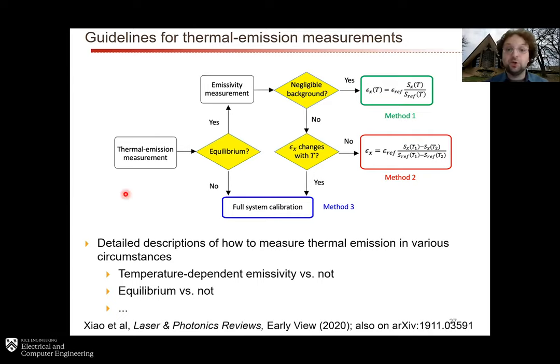And so this is a flowchart from this paper. If you ever find yourself with difficulties doing thermal emission measurements, I recommend you check it out. So for example, you want to do a thermal emission measurement, you can ask, is your thermal emitter in equilibrium or not? If it is, is the background negligible or not, and so forth, and it provides a bunch of different techniques of how to do these measurements as easily as possible, and yet still have them be very accurate and very precise.